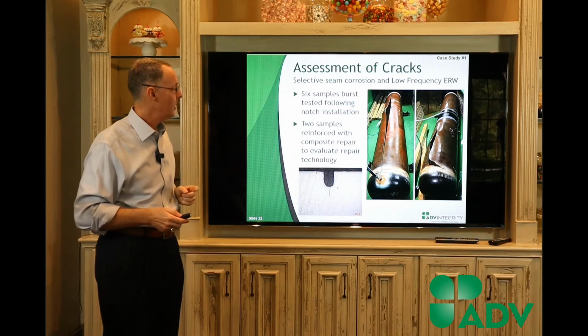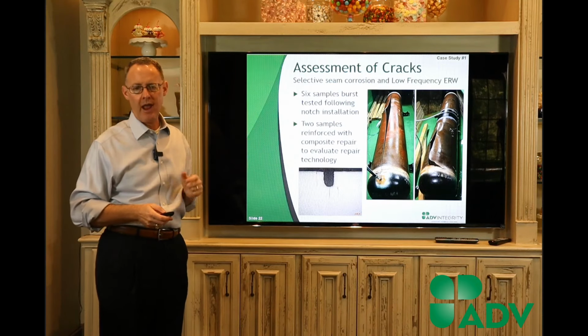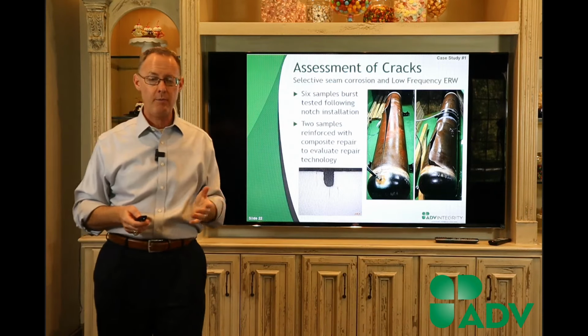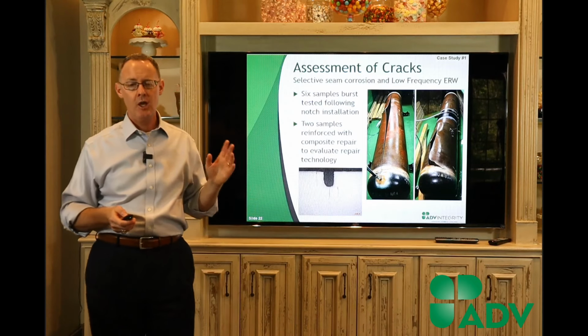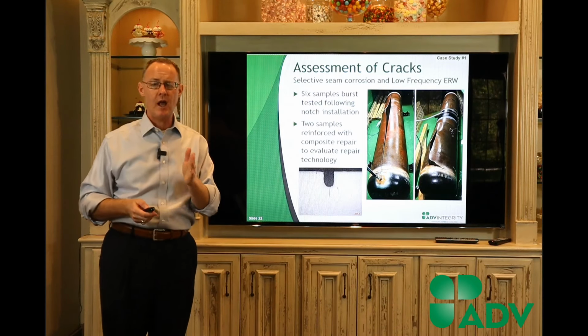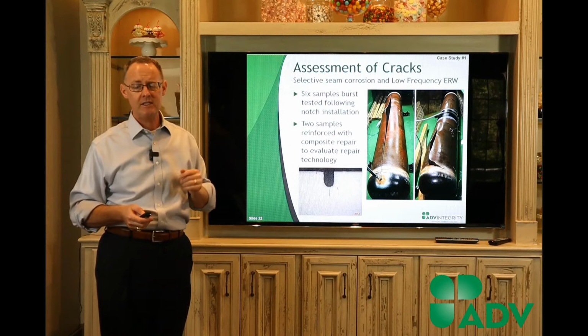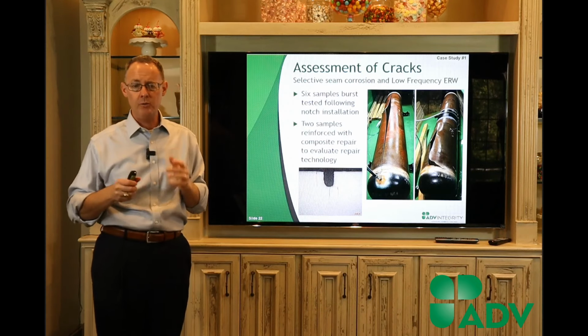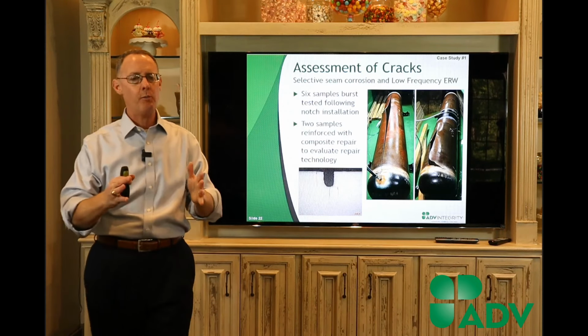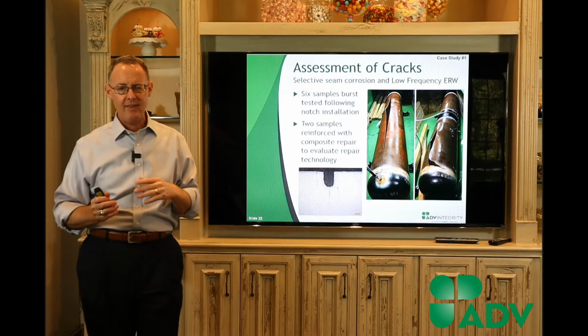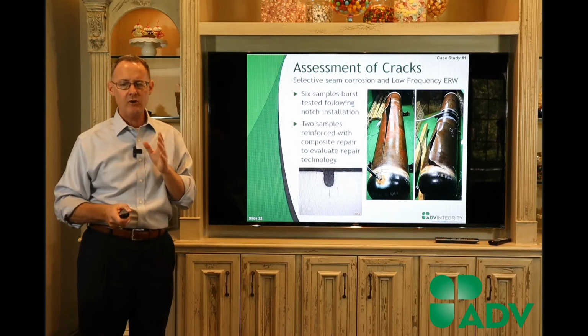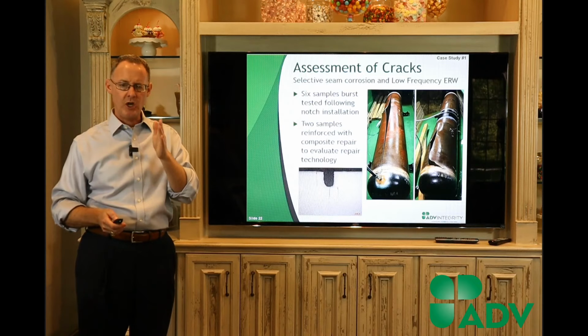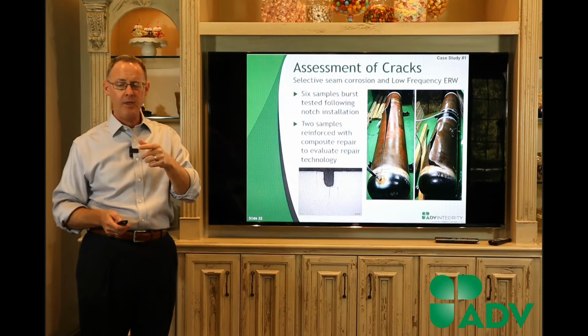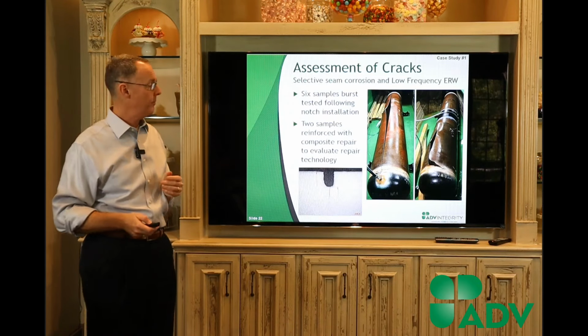that we had created. So just a great example of how we're able to take real pipe. This is pipe probably from the mid-1950s, put an EDM notch in it, do some pre-cycling to get cracking, and then we test it to simulate what's going to happen. So the beauty of this is this went into this operator's integrity management program, and they had confidence in understanding how the feature geometry in terms of length and depth affected the pressure capacity of their pipeline.